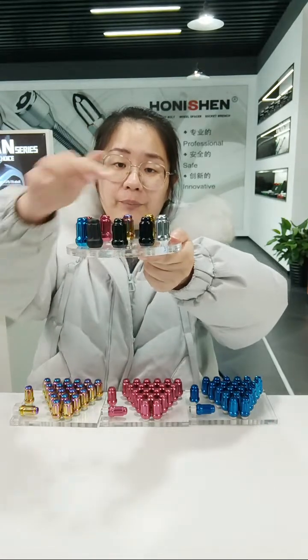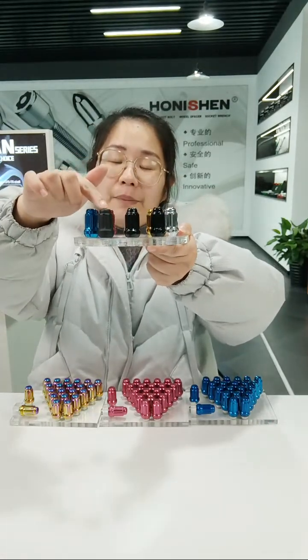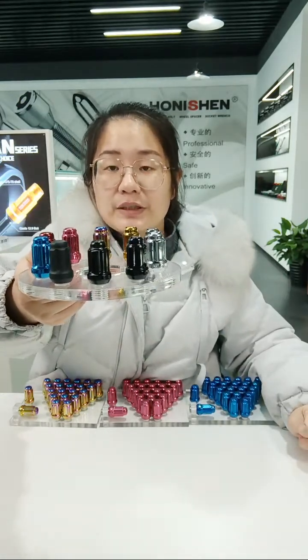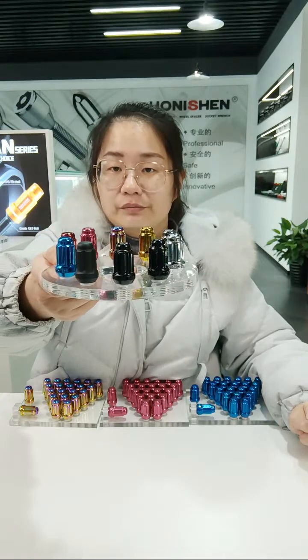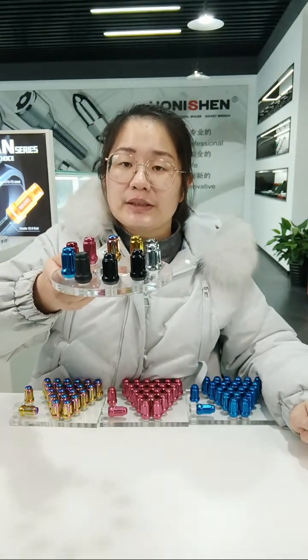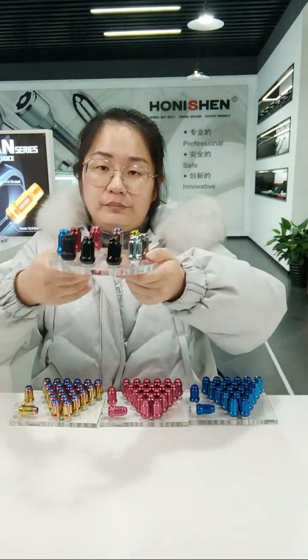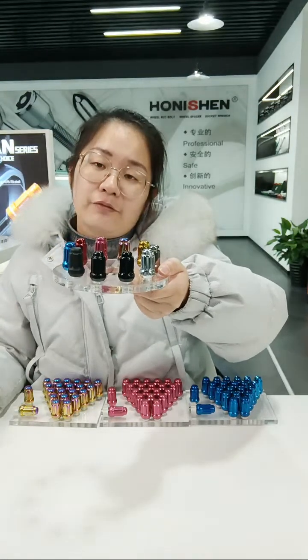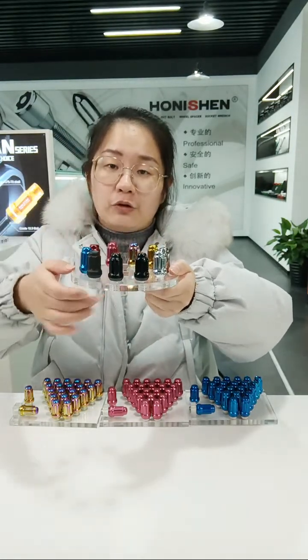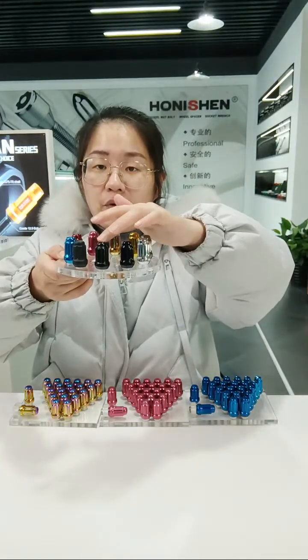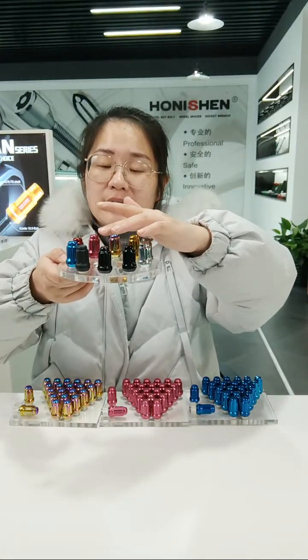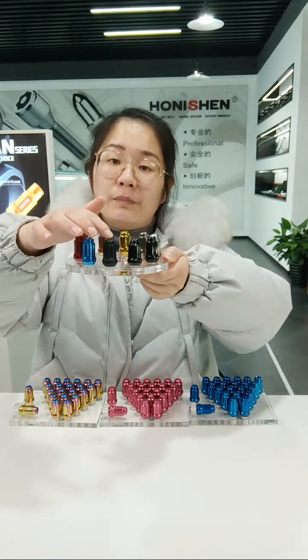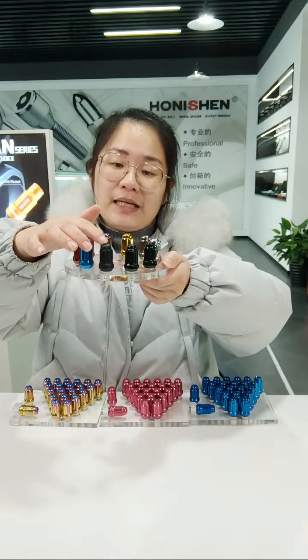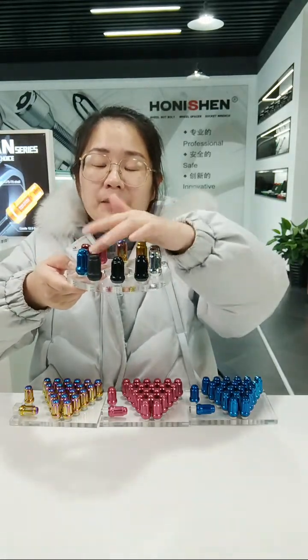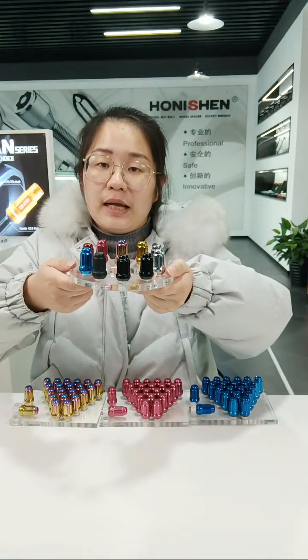There are 3 blacks here: black chrome, black electrophoretic, and matte black. Do you know the difference between the 3 blacks? There are 3 differences between them. Let me show you. For black chrome, the first difference is anti-rust performance. Black chrome could pass over 96 hours salt spray test. Black electrophoretic could pass over 48 hours salt spray test. Matte black could pass over 200 hours salt spray test. So black chrome and matte black have better anti-rust performance.